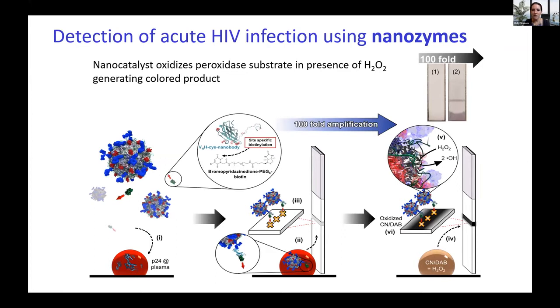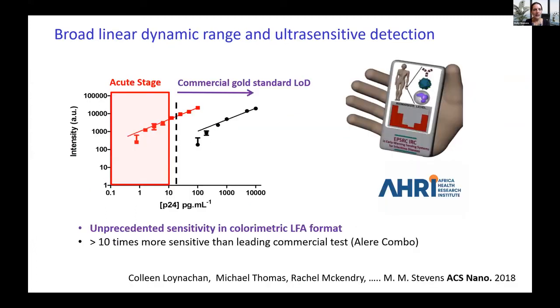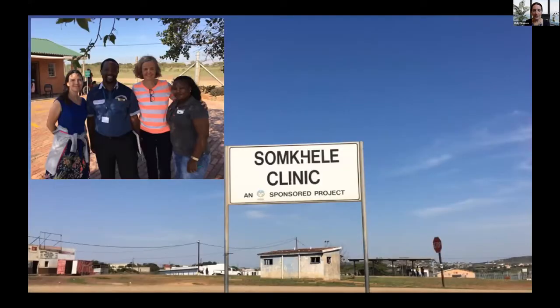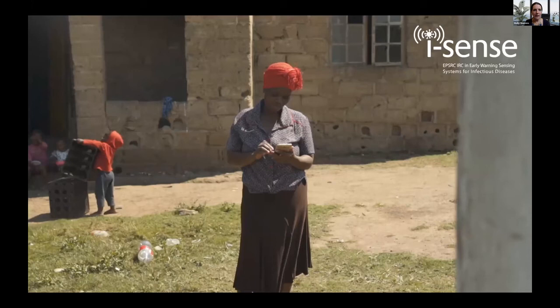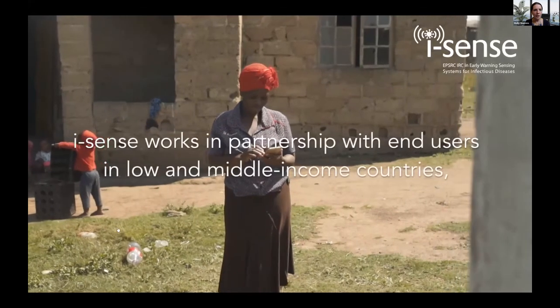So this is 100-fold better than the gold nanoparticle-based lateral flow tests. And actually, at the time we published this back in 2018, it was the most sensitive point-of-care test that had been developed for HIV. And you can see it gets right into that acute stage. So we're working closely with partners in Africa to look at how we can deploy these technologies.